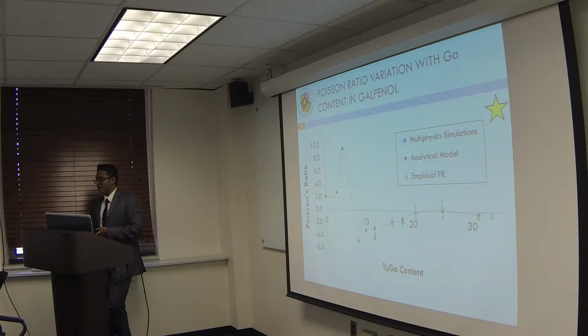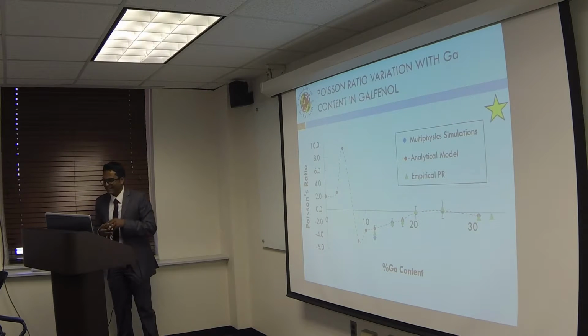Right. As you keep varying the gallium content, you go from one BCC... Yes, it's always BCC, but the lattice point that the gallium atoms occupy is going to depend on the composition. You start with A2 phase, and then you move into DO3. So how do you know that? That's been established. Well, the NSWC folks have pretty well-defined curves for that. Okay, fine.